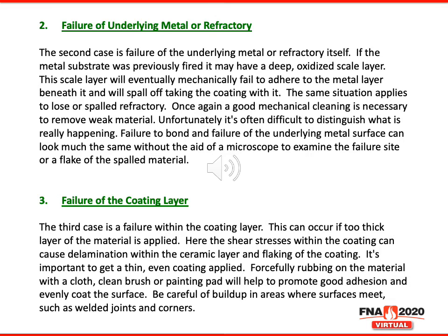The third coating failure, which is failure of the coating layer, is important as well. This third case is a failure within the coating layer, not that the coating fails itself, but because too thick of an application was applied. Here, shear stresses take over and cause delamination within the ceramic layer and flaking of the coating. It is important to get a thin, even coating applied. Forcefully rubbing the coating material with a cloth, clean brush, or painting pad, if a sprayer is not available, will help to promote good adhesion and evenly coat the surface. Always be careful of buildup in areas where surfaces meet, such as welded joints and corners.